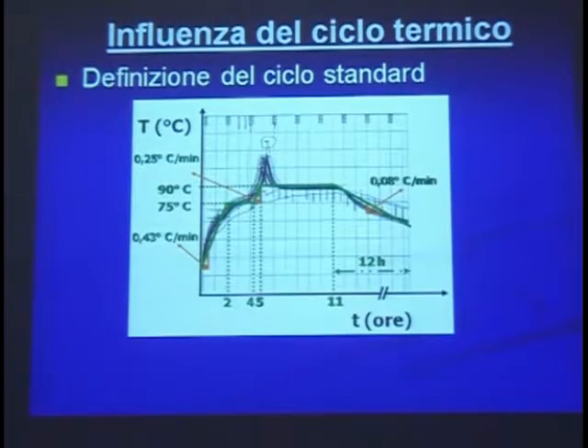This is a bundle of signals coming from the thermocouples placed on the hull of the boat in different places. You may see that there is quite a good correspondence of the real cycle time with the schematic cycle time, except for an exothermal peak that takes place in the early stages of the cross-linking of the resin.